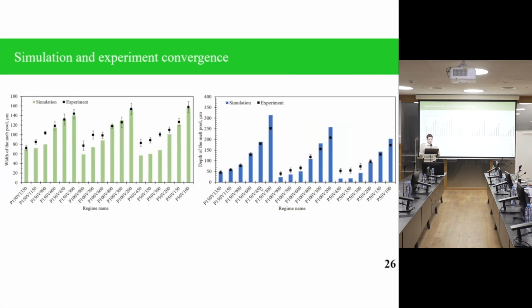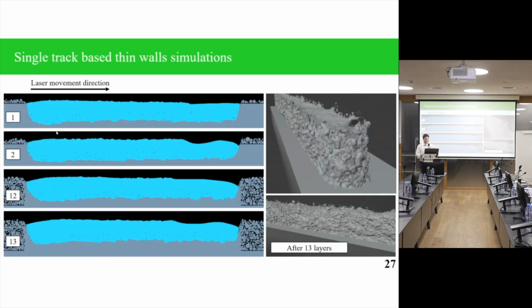And overall convergence between the simulation and the experiment presented on this slide. So we can see comparison between the width of the melt pool and depth, and the convergence is good. We have the highest discrepancy for the regimes where the transition from conductive to keyhole mode happens, and in this case it's complicated to calculate these parameters with required accuracy.